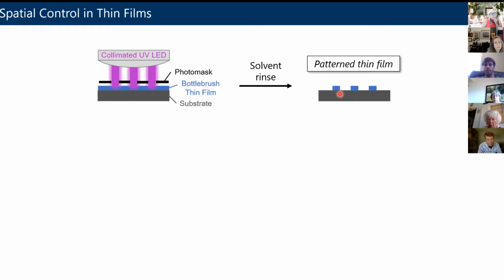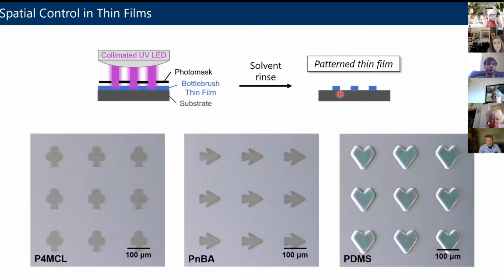You can take this material that's had light shined on it, and you can dissolve away the uncross-linked material in water. Anywhere light did not touch the material will dissolve away in water or some other solvent. Anywhere that light did touch the material will remain because it's cross-linked, it's no longer soluble, everything is linked together. You can see this. We start with different photomasks. I'm a big fan of cards, so we use clubs and spades and hearts. These are regions that have the Bottlebrush material that's super soft. Everything else that's gray washed away. So you've got a physical pattern now of these different objects.